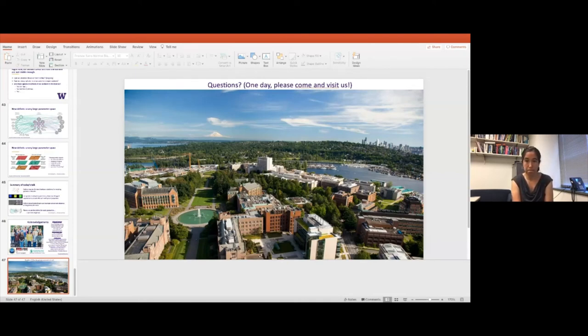And then when you grow the material with controlled defects, wouldn't the intrinsic local stresses be different compared with natural crystal? Wouldn't these stresses get in the way? Yeah, that's an excellent question. So right now, because these are really, really pure materials, the defect does create its own micro stress or strain environment, but as long as it's far enough away from another defect, it should have a similar micro stress environment, again, as in a perfect crystal.